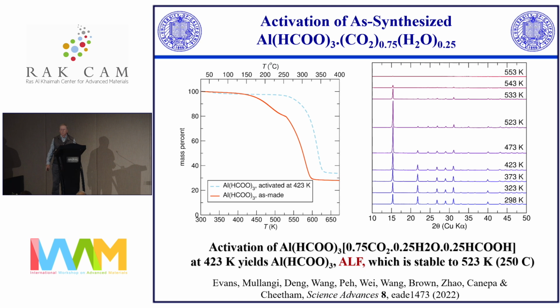and we did all the usual things that you'd expect, like thermogravimetric analysis to show that it does lose all the stuff from the cavities. There's some other stuff in the cavities, but I'll go into the details in a minute. But when the stuff comes out of the cavities on heating, it actually doesn't collapse. And you can see from the X-ray pattern on the right-hand side that it's actually stable to about 250 degrees C before you start to see any collapse of the structure.